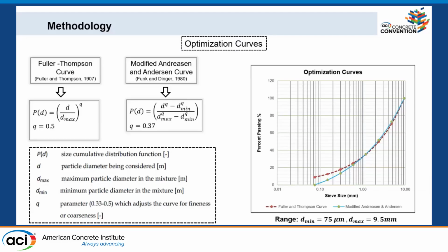For the method, we have picked the Fuller and Thompson model and the modified Andreasen curve, and it works with the sieve size and percent passing. So we have taken these as the standard curves, and we have compared our model to these curves with the particle diameter that we have measured, and the parameter is basically optimized by the Q that is adjusted by the curve of fineness and coarseness.